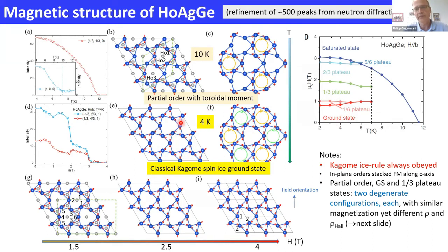Kelvin in zero magnetic field, where you now see that all the magnetic sites participate in the long-range order, and the long-range order can be visualized as such an ordered version of this toroidal order, which is exactly the same as theoretically predicted for the classical Kagome spin ice ground state. And then Khan also did careful measurements in magnetic field and studied the magnetic states in the 1/3, 2/3, and saturated state. And these configurations are shown here.